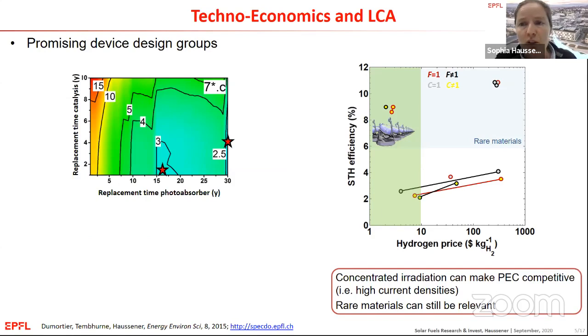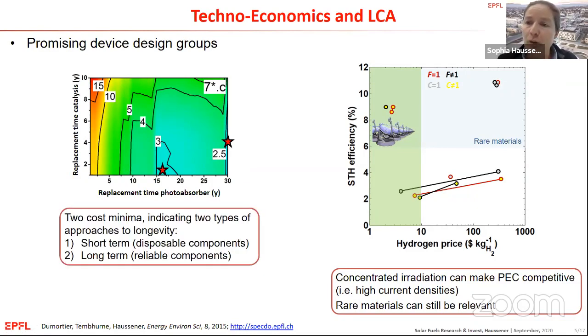And one last comment on this techno-economics, and then I go back to the performance, the technology development. We also try to think, if you have such a device and you potentially want to ensure long lifetimes, you might potentially replace some components of your device during a longer lifetime. And so we try to see what is the advantage if you replace, for example, the catalysis part or replace the photoabsorber part. You get an extra boost in production again, and you pay a little bit for the replacement. And we were able to identify for this particular case two minimums, so two cases where you have a small cost, which led us to conclude another thing, namely that you can follow two approaches in this case. You can either have a device which has components which are sort of a short lifetime.